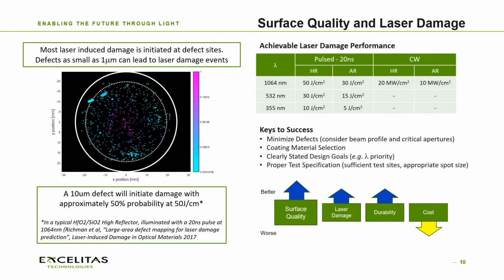When we're in the CW regime, it's a little bit more squishy. The data is a little bit more scarce, but something in the neighborhood of 10 to 20 megawatts per square centimeter can be expected to be acceptable for most high quality, low absorption, high surface quality laser optics. But if we want to be successful in specifying these kinds of optics, we have to minimize defects. That's got to be a critical requirement.